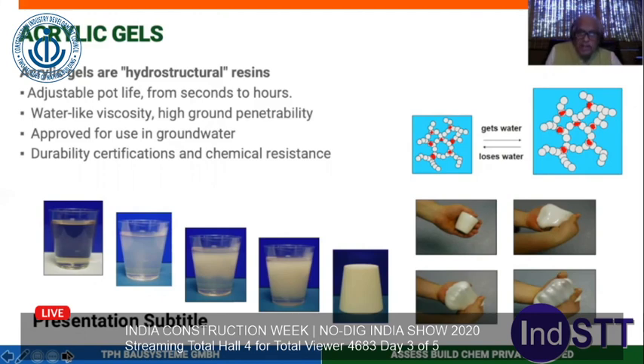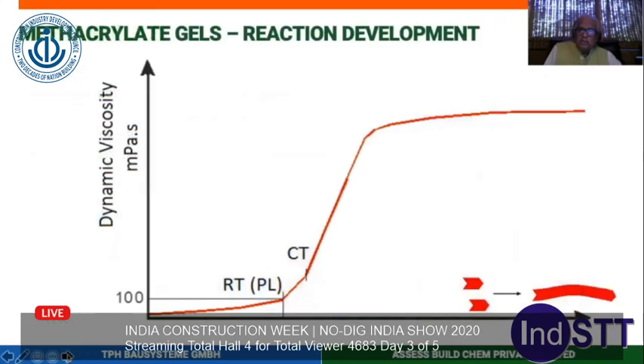There are durability certifications for gels, also for 120 years, with testing in the field for 20 years. Please note, every gel is not a gel. Some gels will just become gels, and after some time they will shrink. Once they shrink, the joint or whatever it is becomes very vulnerable to water entry.